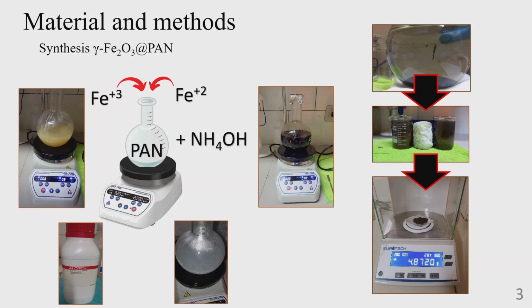For the synthesis of maghemite functionalized with polyacrylonitrile, we started with the synthesis of the sample. The chemical co-precipitation route was followed. For the first sample, the salts of iron 2 and iron 3, iron sulfate and iron chloride, were used in a molar ratio of 1:2. This is the combination of the salts of iron 3 and iron 2, chloride and sulfate.